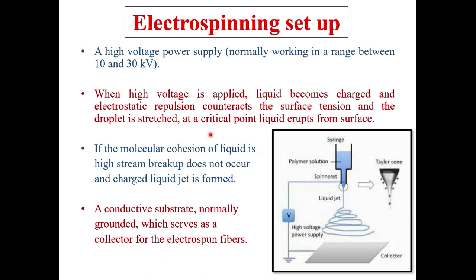When high voltage is applied, from 10 to 30 kilovolts, more than 10, not less than 10, and up to 30 kilovolts is possible, a high voltage power supply is required. When voltage is applied, whatever liquid is in the syringe becomes charged, and electrostatic repulsion counters the surface tension, and the droplet gets stretched. These droplets are stretched and drawn over the collector plate. At a critical point, liquid erupts from the surface. A conductive substrate, normally grounded, serves as a collector for the electrospun nanofiber.